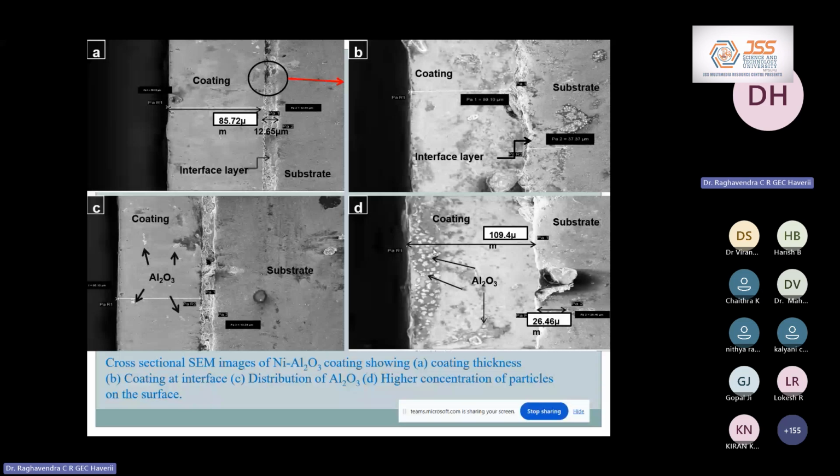The nickel or any copper, the primary material, is attracted towards the cathode, and takes these nanoparticles along with it and makes them adhere to the substrate materials. That makes the nanoparticles with a higher concentration concentrate on one area.